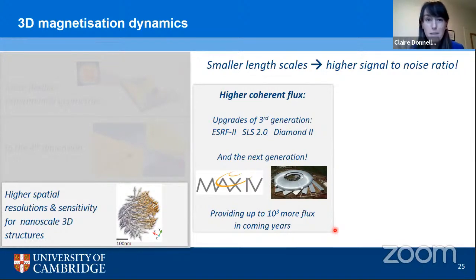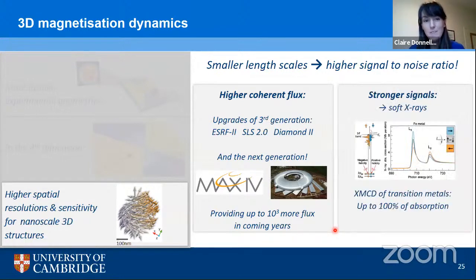But perhaps a more immediately available route to higher signal-to-noise ratio is going to stronger signals in the first place. And for that, we can go to lower energy X-rays, so soft X-rays, where we have a much stronger X-ray magnetic circular dichroism. Although we're limited to, let's say, thinner samples, so a few hundred nanometers of material, we can have XMCD signals of up to 100% of the absorption. And for this reason, we